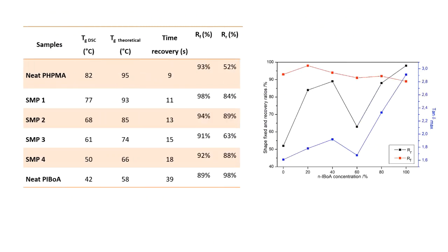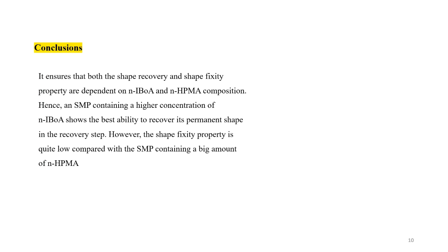Combined with the molecular dynamics simulation results, it is verified that the amount of isobornyl acrylate has a significant impact on the shape memory performance, including shape recovery and shape fixity. The system shows a good recovery performance of around 88% when the isobornyl acrylate increases to a certain value, while the HPMA improves the shape fixity of the systems. Finally, it can be concluded that the shape memory polymer containing a higher concentration of isobornyl acrylate shows the best ability to recover its permanent shape in the recovery step. However, the shape fixity property is quite low compared with the SMP containing a big amount of HPMA.